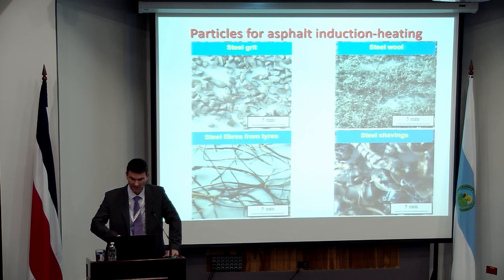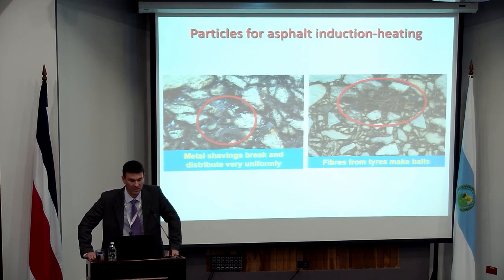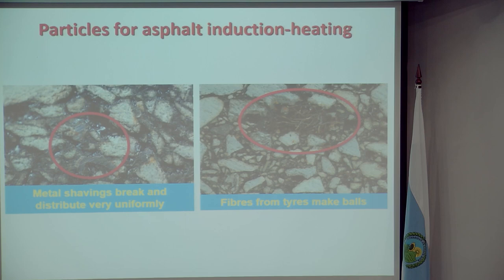The ones that we've looked at, we'll just quickly show you some differences in terms of these individual materials. Some of them spread out really nicely. So on the left-hand side, we've got the metal shavings. They can be added and distributed in the asphalt mixtures just by adding them during the simple mixing process. So while you're adding your aggregate and mixing it and then adding your bitumen, if you add in your metal shavings just before you add the bitumen, you get a fairly uniform dispersion. The fibers from car tires tended to cluster and tended to bulk up in terms of little balls of fibers.